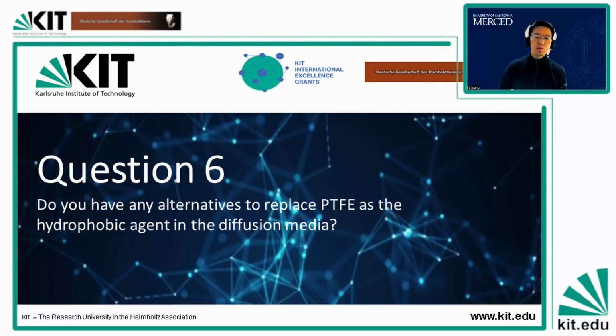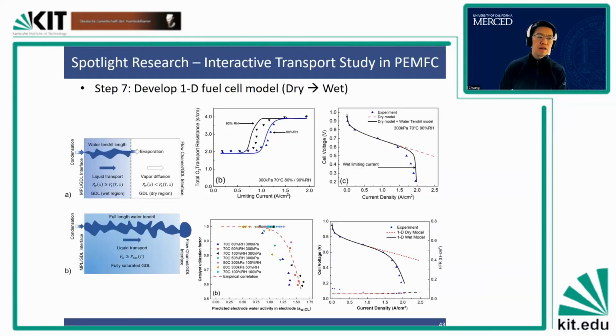Before we get rid of PTFE, we probably have to find ways to modify our Nafion, because Nafion is modified PTFE and it's right next to the catalyst layer. And so that is much more worrisome. PTFE inside the gas diffusion layer and microporous layer is a little bit farther away from the platinum carbon, and so potentially not as detrimental. But the Nafion structure, PTFE structure, the phosphoric acid, fluorine, these are right inside the catalyst layer, and we probably need to find ways to mitigate or modify those first. If you have someone in the audience who is more material oriented, who can modify carbon fiber and try to implement various levels of hydrophobicity, I think that would be an innovation.